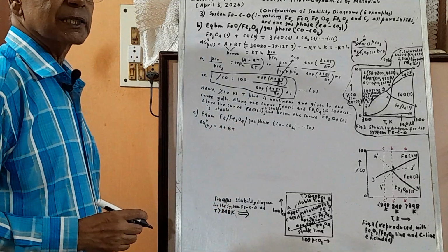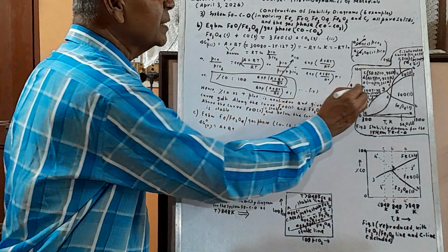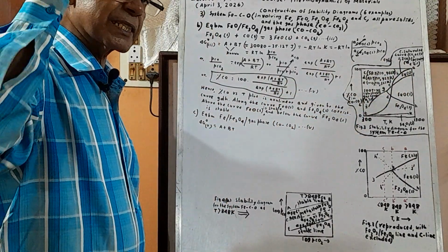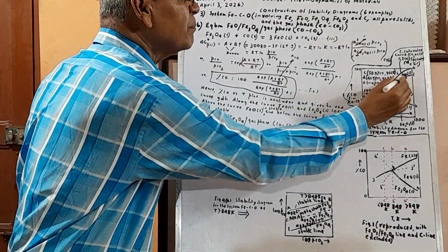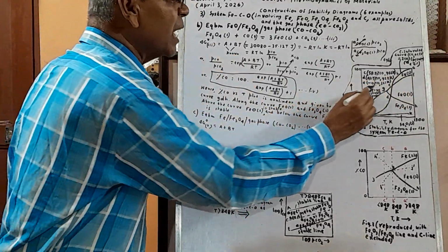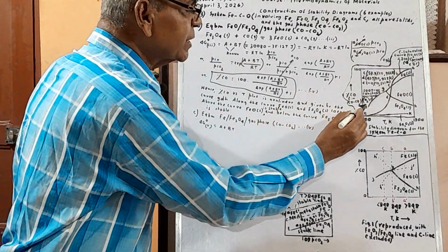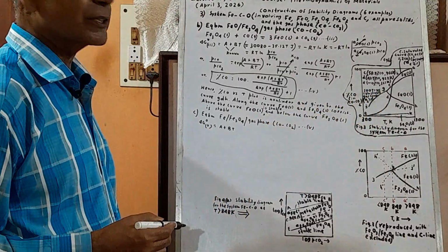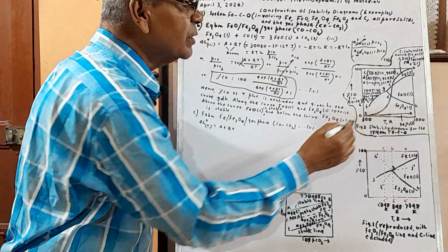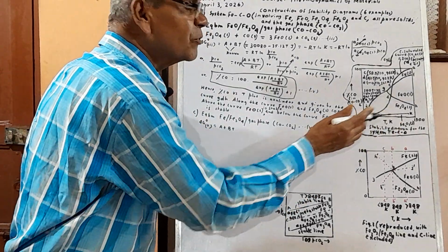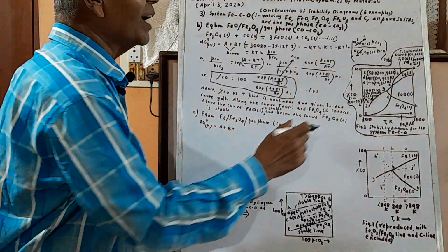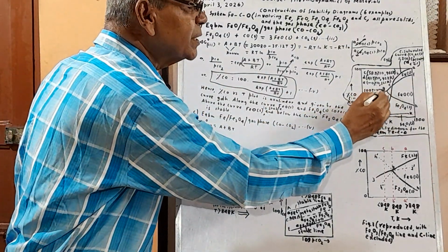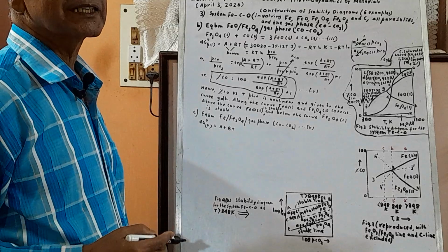I tell you one thing in passing, you see, this is actually rising upwards. The last step, the FeO equilibrium curve, is rising upwards. Now this we are going to draw, this Fe3O4 is also rising upwards. And the bottom one, Fe2O3 to Fe3O4, is also rising upward. But the one that we finished just now, FeO to Fe, is descending.